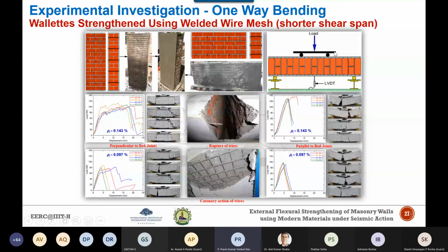Okay, it is interesting to note that the flexural failure is brittle. If you see the load displacement curves, for the flexural failure they are much more brittle, whereas the shear failure has some ductility. So here it is also related to how this strengthening reinforcement basically failed. This brittle flexural failure is accompanied by the rupture of the wire mesh and can be attributed to a very low reinforcement ratio, resulting in a very shallow depth of the neutral axis. Whereas in case of the shear failures, the gradual sliding has been registered by the catenary action of the welded wire mesh, which is resulting in a slightly ductile failure.